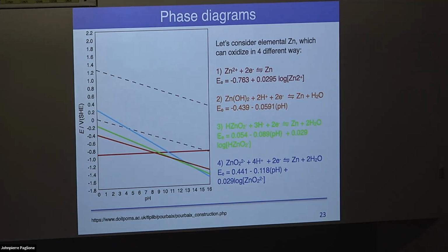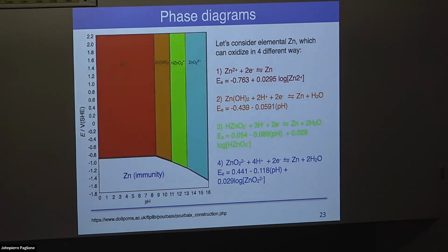What these tell you is that below this electrochemical potential, for example, this first reaction, you'll have zinc 2+ being reduced to zinc. So below the red line, you'll have zinc metal. Same thing with the orange line. Below the orange line, you have zinc metal. Below the green line, you have zinc metal. And below the blue line, you have zinc metal. So what does that tell you? It tells you that below all those lines, you have zinc being completely immune. So if you have enough reducing environment, you put your zinc in the water, it won't do anything.